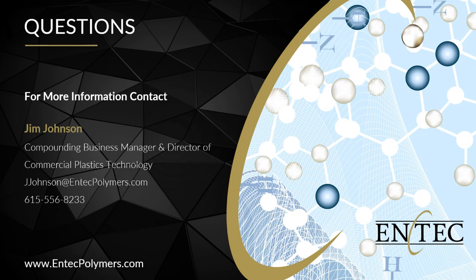Can we compatibilize PET and PE? There are a few research studies saying it is possible. Is it practically possible? Yes, absolutely, because once again, we would utilize a glycidyl methacrylate copolymer where the backbone is an acrylate and has the compatibility to both polyethylene and PET. However, the glycidyl methacrylate would now be a reactive compatibilizer, and they work very, very well to compatibilize PET to polyethylene and polypropylene.